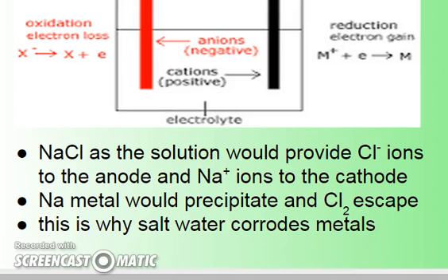And this is why salt water corrodes metals, because if you have any two metals at all, for example, the Statue of Liberty is copper plated, or is copper on the outside, and it's attached with metal rivets to an iron shell or an iron skeleton inside. And then they put it in this big salty area. They put it on an island out in the middle of the ocean. And so all that salt water with two different metals basically formed an electrolytic cell, when there was mist and stuff in the air. So it wasn't a big surprise when all of a sudden those rivets started corroding off and the whole copper shell started sagging off. You're probably too young to remember, but they had a huge restoration project of that.